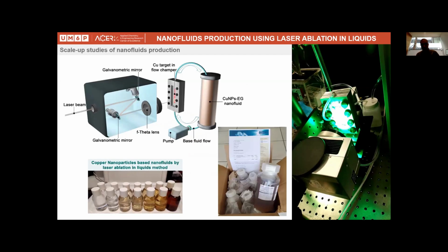So for us, we tested this method, of course, with other colleagues, collaborators from Germany. The system is very simple here. You have a source of laser, so you can use galvanometric mirrors to scan the laser beam on a target which is inside the flow chamber. This is the conventional heat transfer fluid. You can pump it through the flow chamber and do ablation of your target, so you can generate nanoparticles directly.